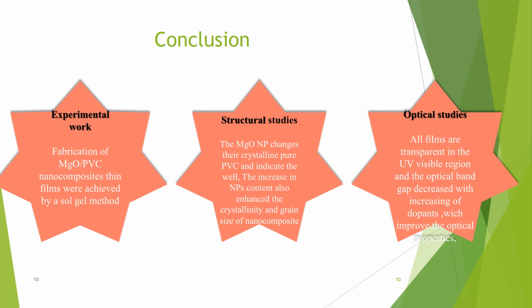The optical studies demonstrate that all films are transparent in the UV visible region, and the optical band gap decreased with increasing dopant, which improves the optical properties and can be used as promising materials for optical display system applications and also for dye removal.